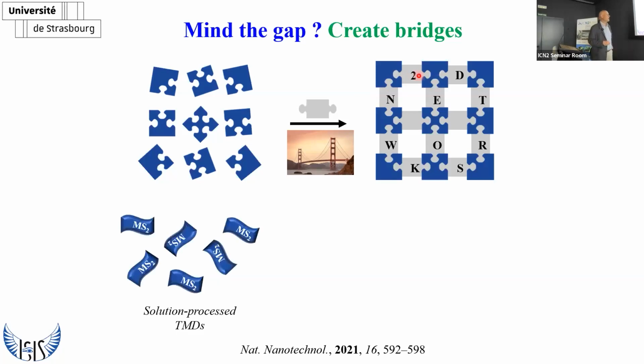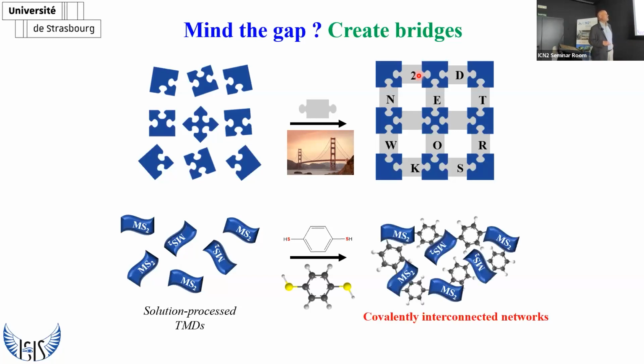Now, in a more chemical way of expressing this, we have this solution-processed disulfide, which we've proven to work with molybdenum disulfide, rhenium disulfide, and tungsten disulfide, and then we combine this with a conjugated molecule which has two anchoring groups, two thiol groups in the para position of a phenyl ring. This way we can covalently interconnect the network, which means we have two effects at the same time. First, we heal the sulfur vacancies that are on the basal plane and at the edges of the MoS2 or the other disulfide, and we covalently bridge the adjacent nanosheets. So that is the concept.